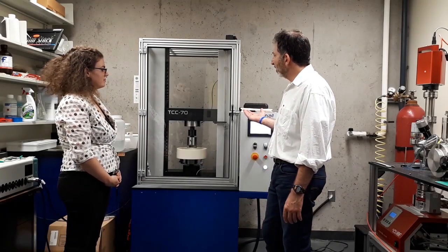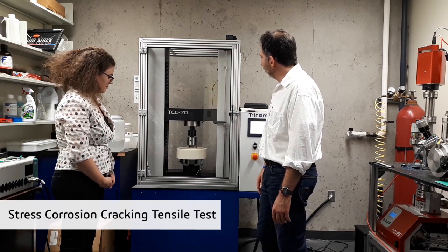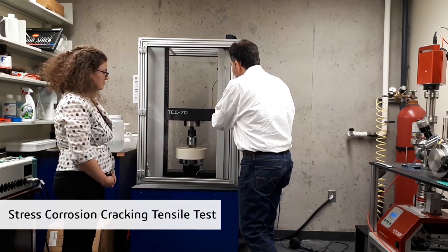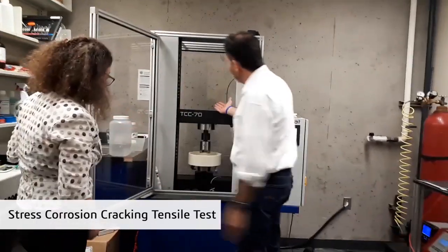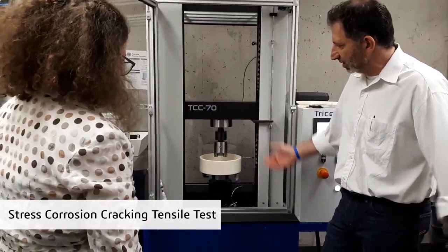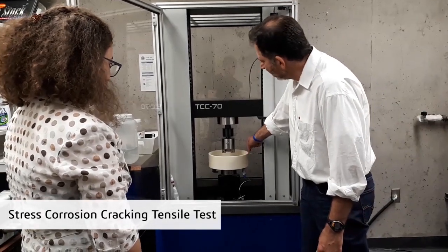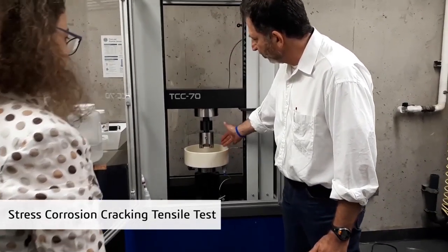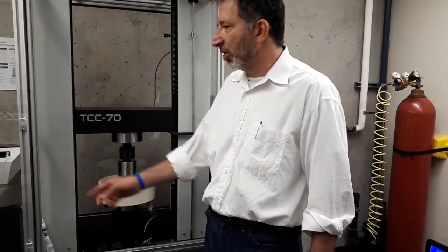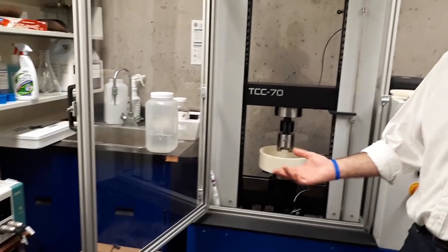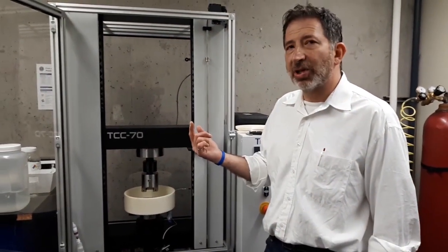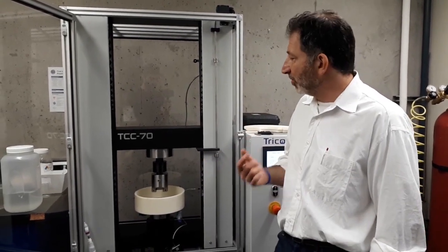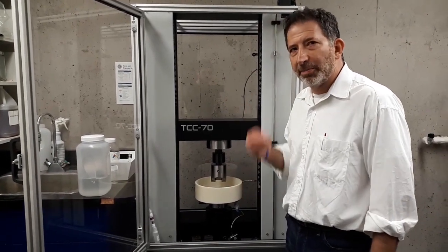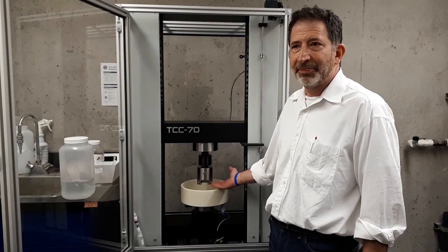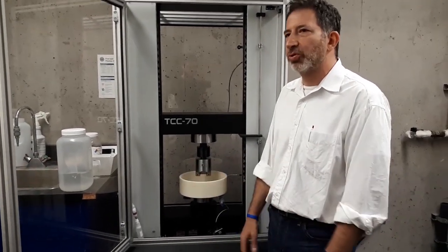So this is what we call a stress corrosion cracking tensile frame. We put a sample inside this tensile frame. For all intents and purposes, it looks exactly like a tensile tester, but it also has an environmental chamber. This chamber will be filled with sodium chloride solution, and it's hooked up to a potentiostat, which is over there. Through that potentiostat, we can impose a potential or a current, and that essentially generates hydrogen because it's creating an electrolytic cell. It generates hydrogen at the surface of the sample, and we can pump hydrogen into the material as the sample is being tested. As it's being strained, it's absorbing hydrogen.